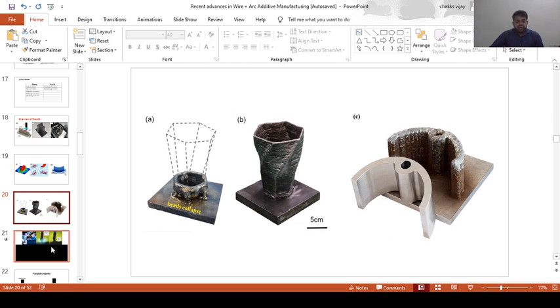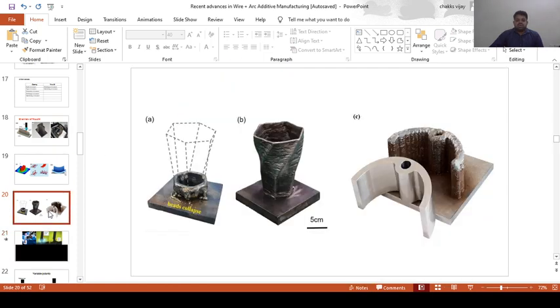For doing this, we have to optimize the molten pool flow dynamics, which is one of the most essential things we should plan prior to deposition. After a lot of pilot experiments, we optimize the process parameters. In a conventional MIG process, we optimize each parameter manually, whereas cold metal transfer welding, which is a modified form of the MIG welding process, was developed by Fronius Technology.